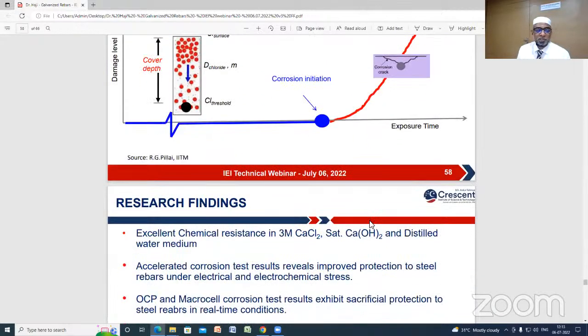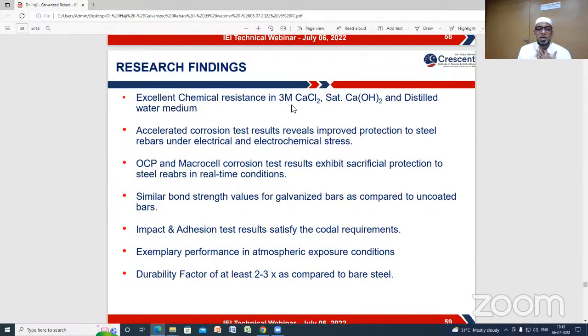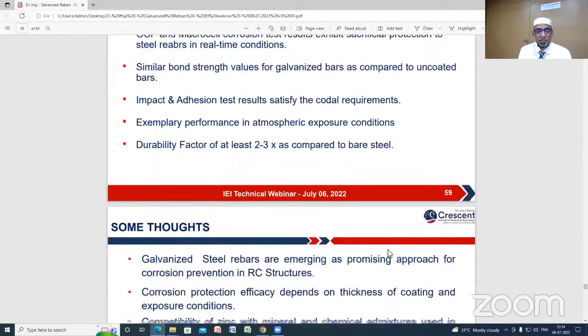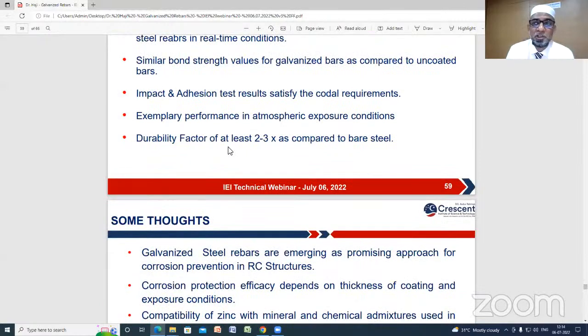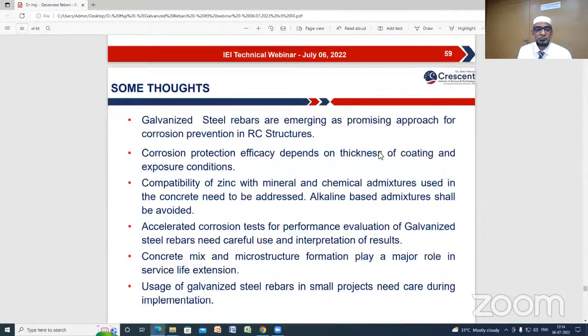That's a good sign. So research findings show the galvanized rebars offer excellent resistance against chloride, calcium hydroxide, and water mediums, and all the test results show improved corrosion resistance. There are similar bond strength values, and impact and adhesion are also good compared to other coatings, with exemplary performance in atmospheric exposure. The durability factor, or performance factor, is 2 to 3 times more compared to normal steel.